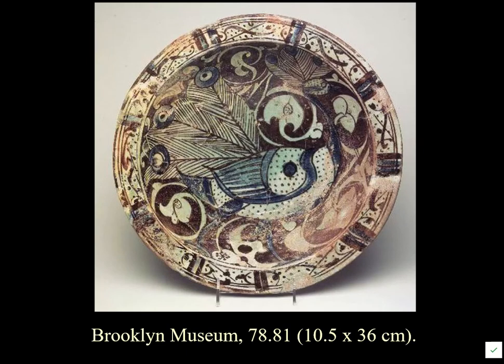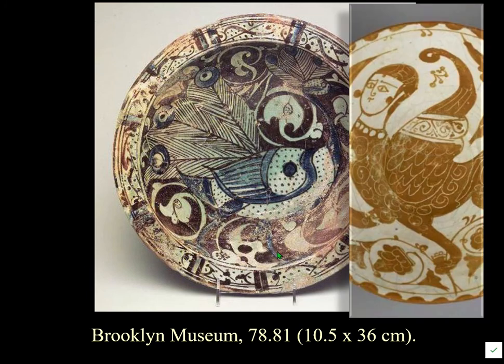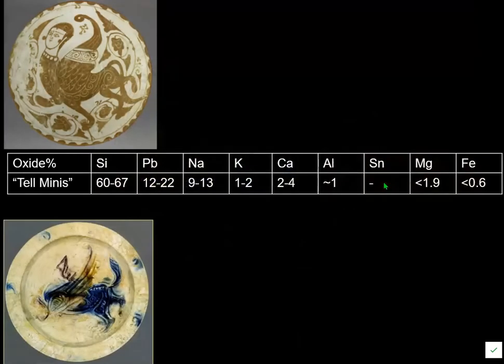The theory for why underglaze painted ware was developed relates to two types of lustre paint: one copper-rich with hardly any silver, and another silver-rich. The glaze type also differs — one is alkali, the other lead-alkali. Looking at the Tell Minis wares: Laqabi ware has lead and alkalis in the glaze. Then they switched to making alkali-glazed lustre wares with copper-rich lustre paint.